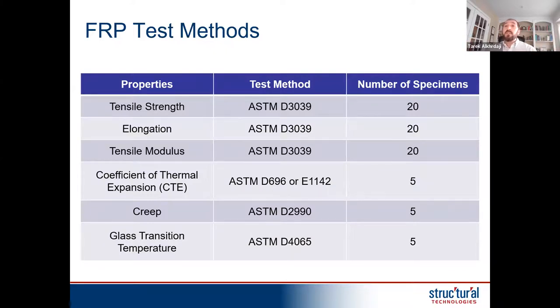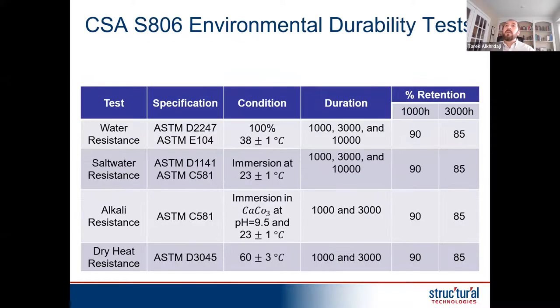Test methods: there are standard test methods, currently ASTM, for all the properties of the FRP. The manufacturers of all these fabrics and materials list their mechanical properties: tensile strength, tensile modulus, elongation, compressive strength, et cetera. On top of that, there are also requirements for durability testing. To determine the properties, you also have to expose these materials to aggressive environments, like you can see here: water resistance, salt water, alkali resistance, dry heat resistance, with guidance about the condition, the concentration, or the temperature for the testing.